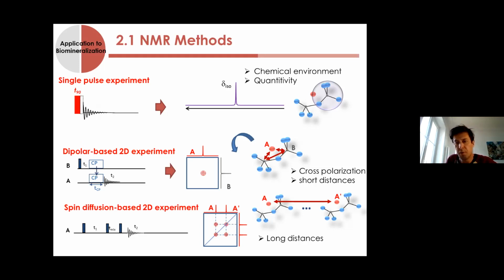It works well with short distances, and in the case of 2-dimensional experiments, you can access that information through the observation of what we call a cross-peak resonance, shown here for instance, which characterizes the proximity between resonance A and resonance B, because A and B are close in space.